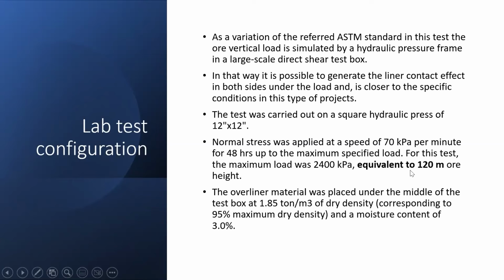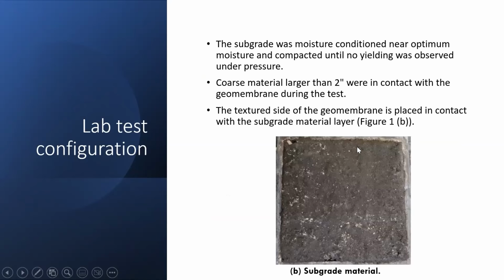The important thing in this case is that the test was developed at the beginning for an equivalent height of 120 meters, and we took the overliner samples, the same samples they were trying to use, and put them at a density of 1.85 tons per cubic meter and a moisture content of 3%. Prepared subgrade conditions with no yielding was observed under pressure, and the coarse material larger than 2 inches was in contact with the geomembrane during the test.